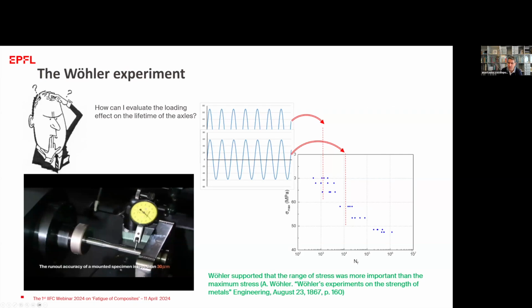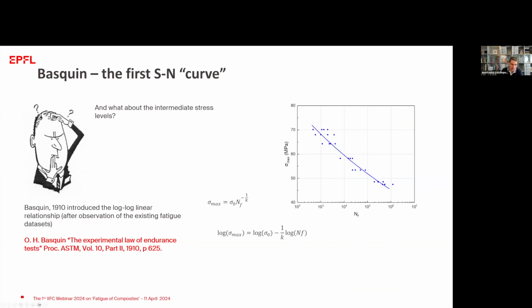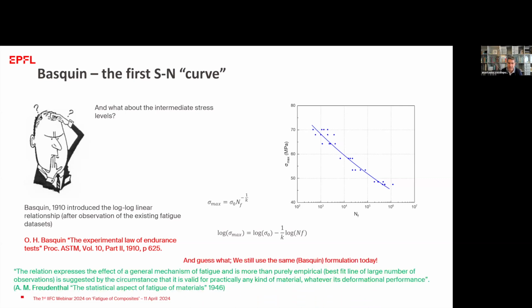Because what we see here, what Wöhler did was only putting the data on the SN diagram, as we call it here. So we had another person, this Basquin, another engineer that introduced a line, and he claimed that a logarithmic relationship, which means a linear relationship in the logarithm of sigma and logarithm of number of cycles, is appropriate to fit well the experimental data. And this first, if you like, SN curve has been introduced in 1910. And guess what? It is still used today.